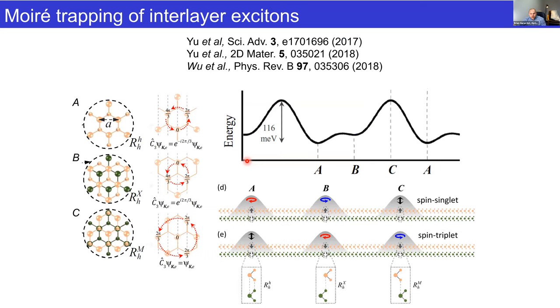Maybe just without going into detail, the microscopic theory of how carriers and photons should interact in these Moiré confined lattices has been worked out. The basic idea is that due to a certain atomic registry, one gets a certain polarization for a certain type of spin pairing. So for instance, for spin singlet pairing of the electron and hole at atomic registry trapping site A, where the two layers are aligned, one gets a right-hand circular polarization for the spin singlet, or a Z polarization for the spin triplet, and so on. So at least mathematically, one can work out what's expected of the photon properties for emitters at certain atomic registries.